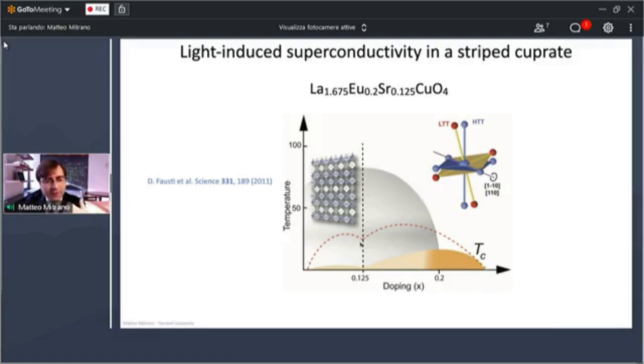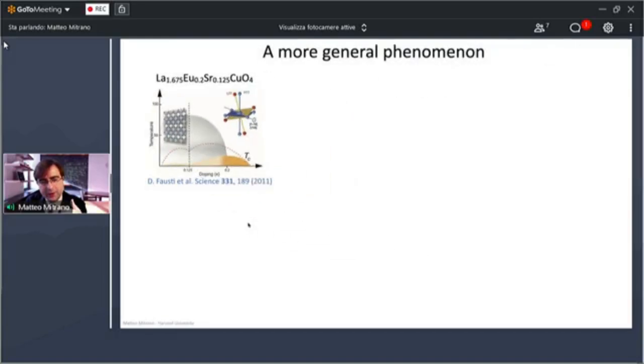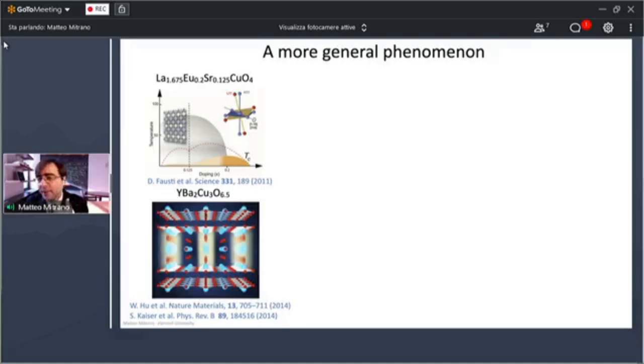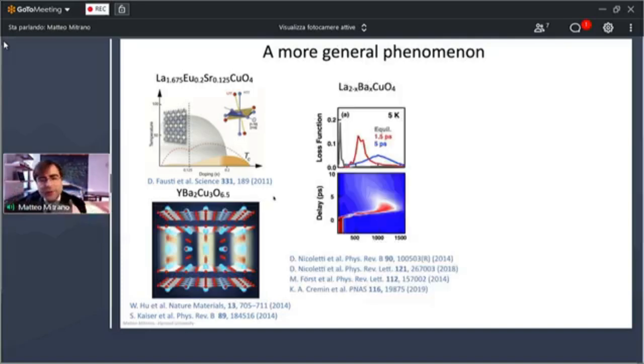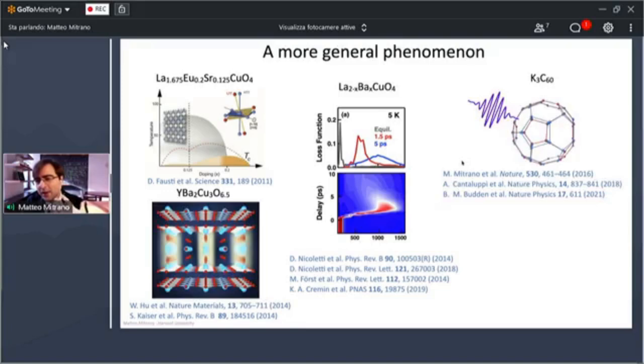Now, this phenomenon was then detected over many years in other materials, in YBCO as well. That is another cuprate with double layers. In LBCO, that is another cuprate, and then some sort of a big shift in our thinking about this phenomenon that seemed somehow restricted to the cuprates was my observation of gapping and so potential light-induced superconductivity in K3C60. And therefore an organic material that is very structurally different with respect to the cuprates.